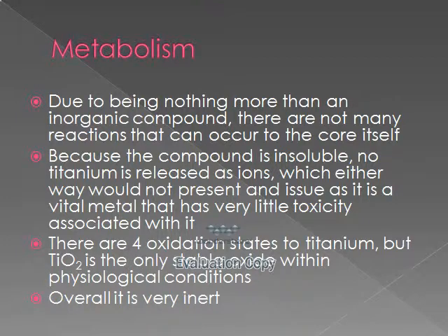Because titanium dioxide nanoparticles are nothing more than inorganic compounds, there are not many reactions that can occur to the core itself. The compound is insoluble, so very little titanium is released as ions, which either way would not present any issue, as it is a vital metal to the body and has very little toxicity associated with it.